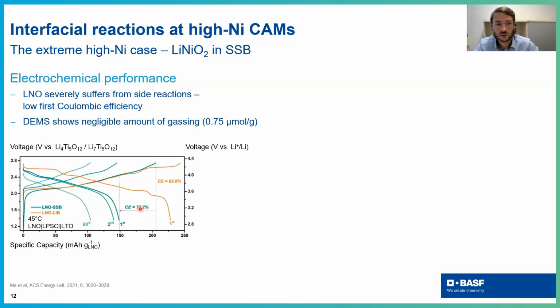Interestingly, if you make DEMS measurements, so the analysis of the gases which are evolving from these two types of cells, you will observe that actually the gases which are coming out of the lithium nickel oxide in the solid state battery are really negligible. So if you compare the solid state battery and the gases coming out, they are actually much less than what you would observe in a conventional lithium-ion battery. And this is actually already very interesting. So the question is, what is happening?